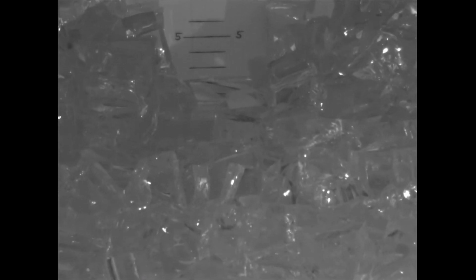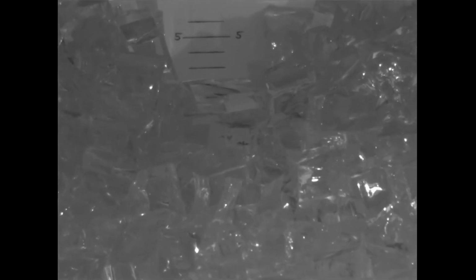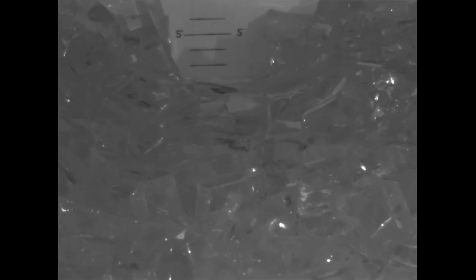I reduced it just to look across the mold of the far side. I won't bore you with the wide-angle views, but this is the most exciting part. As the temperature rises, the glass just looks like lumps of jello, forms a layer about 5 or 6 inches deep, and as it continues to get more fluid, it drops into the mold very quickly. There's bubbles at the surface that come up and pop, and you want glass about 2 inches deep at the edge, or at the end when the glass fully runs into the mold. And that's what you have.